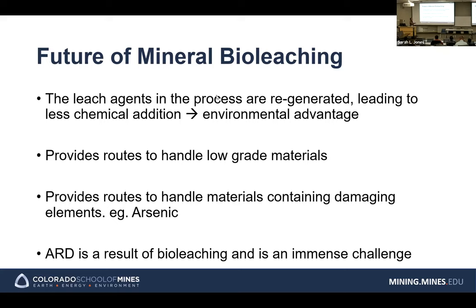And it provides a route to handle materials containing some damaging elements such as arsenic and selenium and other material. So if you have arsenic in a copper concentrate, if you send it to the smelter, you're going to get some penalty fines. And using a bio process, we can treat those concentrates. And at the same time, we can also get around the toxicity of the arsenic. So that's one of the options.